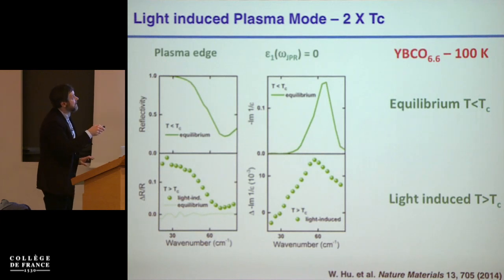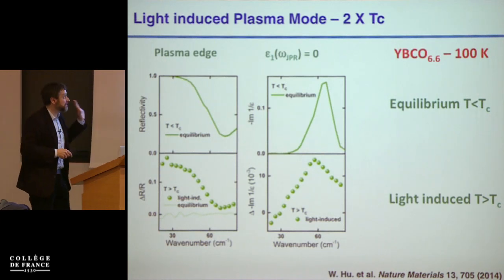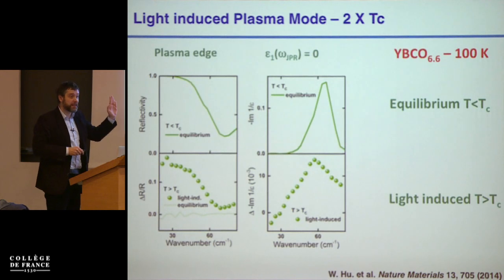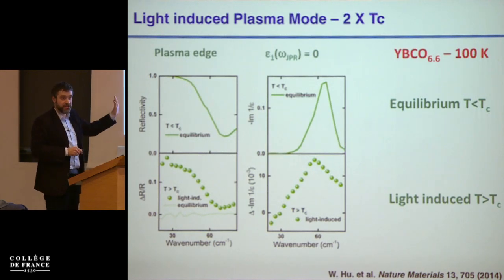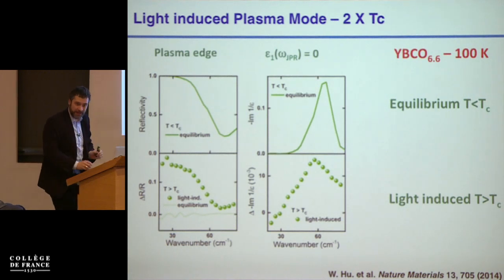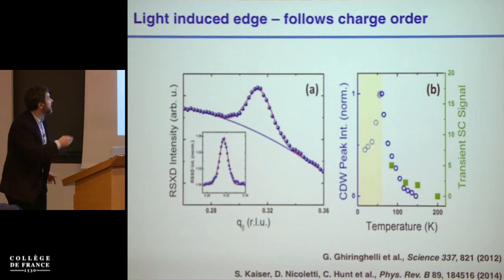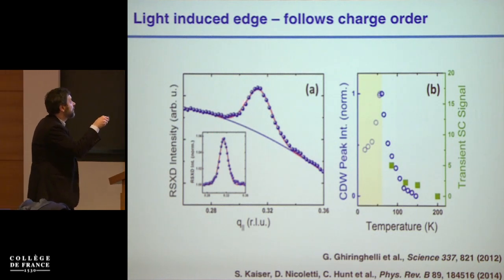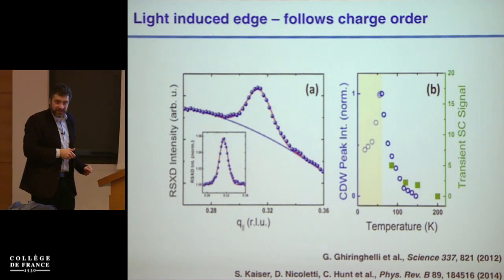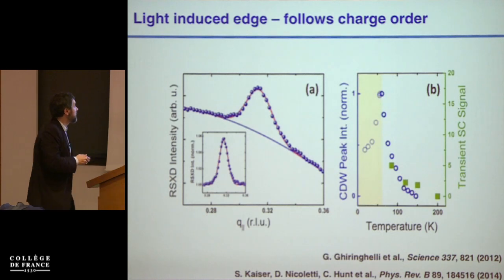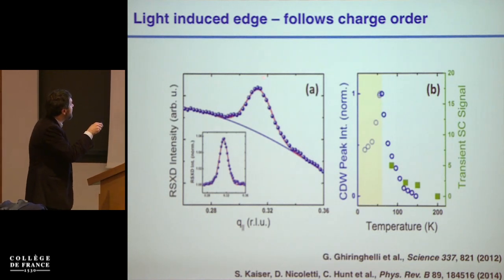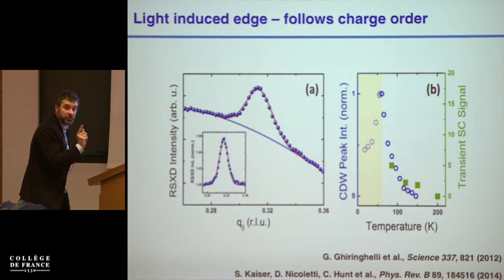Yeah, this is 2 times above TC at about 100 Kelvin. But so far, this is still a 1/8 doped compound. So this observation is equivalent to the observation that I already showed you in LESCO. Okay? And also, if you take the charge order peak in this compound, which you can measure, again at the X-ray free electron laser, after lots of struggling in trying to get beam time, and this is a static peak now you can measure in these experiments, you can see how this static peak goes away at the same temperature where our light-induced plasma edge goes away.